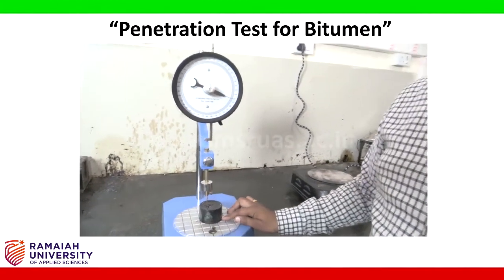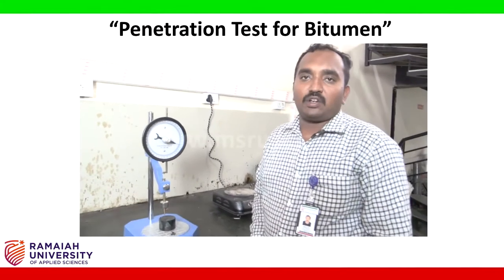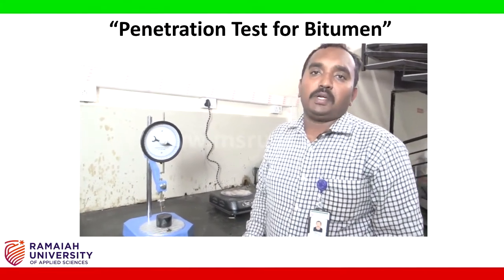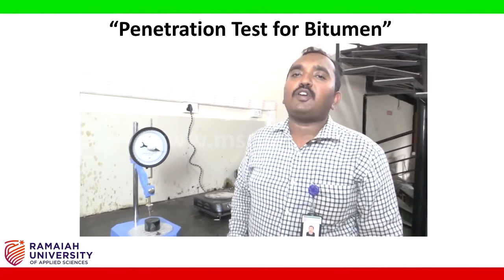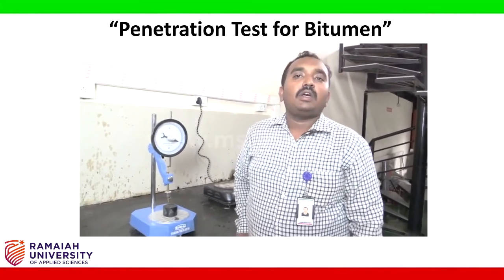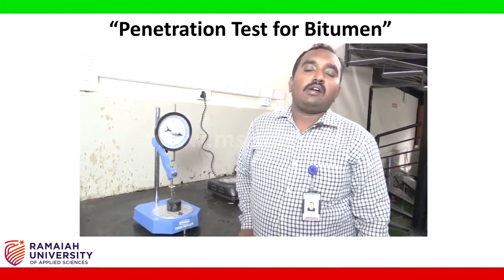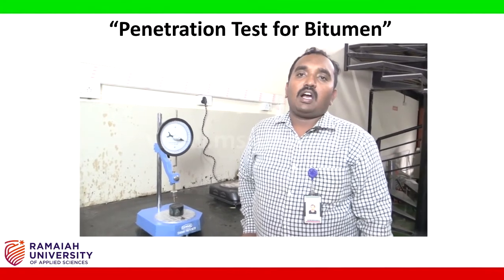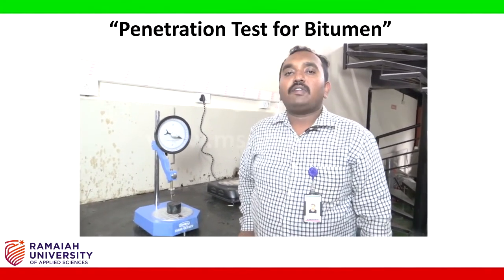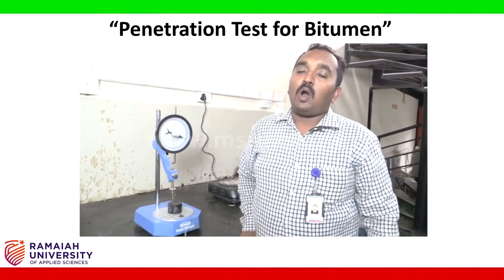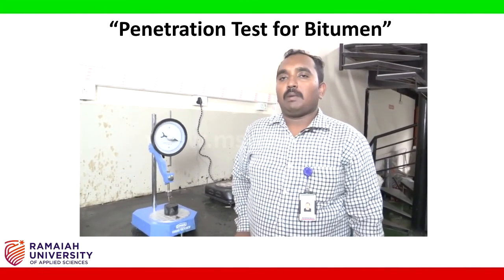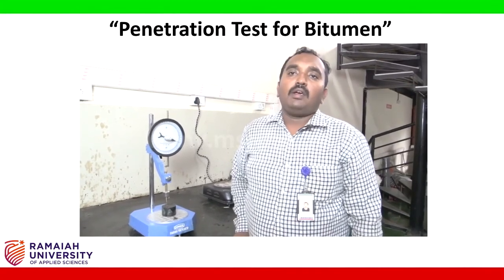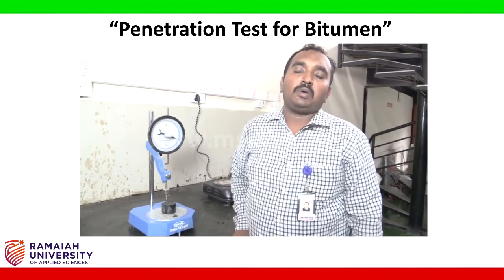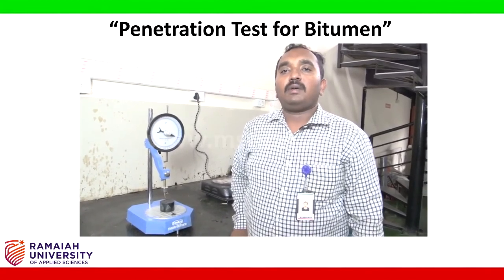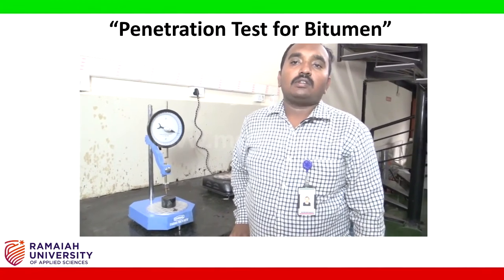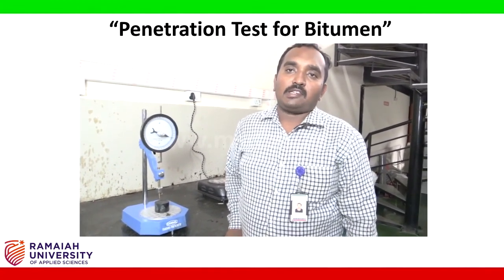The average depth of penetration gives you the penetration of the bitumen, and it gives you the grade of the bitumen. If your penetration value is between 30 to 40, it's called 30/40 grade bitumen. If between 60 to 70, it's called 60/70 grade bitumen. And if somewhere between 80 to 100, we call it 80/100 grade bitumen. For hotter climates, it's preferable to use 30/40 grade bitumen, that is hard bitumen. For cooler climates or cold regions, we use 80/100 grade bitumen. This completes your penetration test experiment.